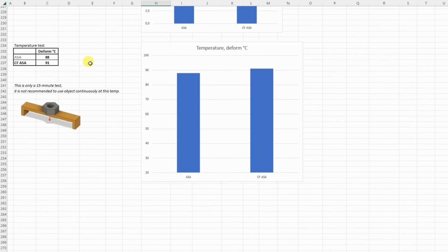And the temperature is something I expected, so ASA starts with deformation around 90-95 degrees Celsius, and that was the case here. The carbon fiber version may have a little bit bigger temperature resistance, but only 2 or 3 degrees Celsius.